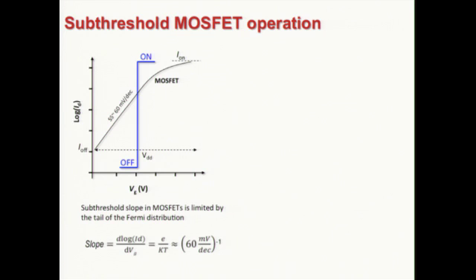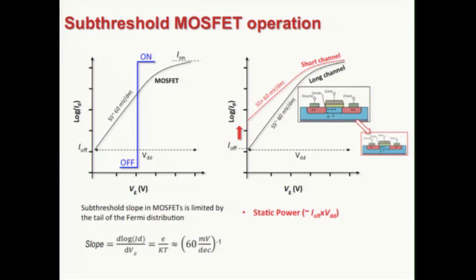Well, the MOSFET that I already explained is not an ideal transistor. So we don't have such an abrupt transition from off to on. There is a slope here, which at room temperature, the best is 60 millivolt per decade. So we need a substantial gate voltage to switch from off to the on state. And we need to be careful with the device architecture, because when we scale it down and make the transistor smaller, the slope can actually get worse. That can be easily affected by parasitic short channel effects, so we need to optimize the device structure in each generation to improve the gate electrostatic control over the channel to have the subthreshold slope close to 60 millivolt per decade.